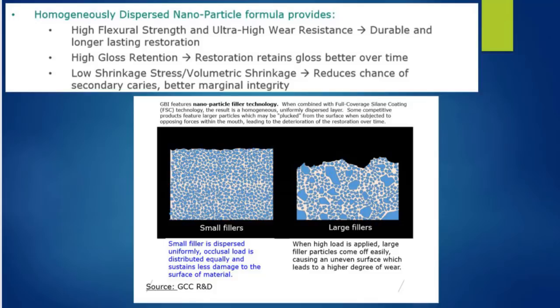Why? What is the difference between a nanoparticle filler and a large filler? When we get a break at the surface or breakdown at the surface, when a large particle filler falls out or breaks away, chips away, that leaves more surface roughness and will have less gloss and a higher likelihood both for plaque retention and for loss of polish and surface roughness to the tooth as well. Certainly better marginal integrity.